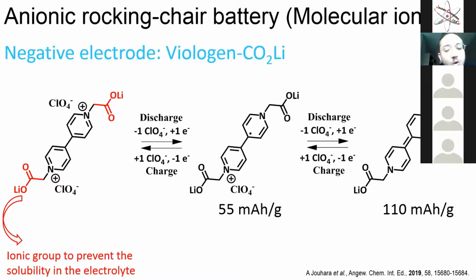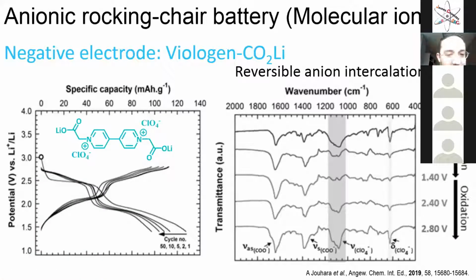This work has been published in Angewandte Chemie, and it is a nice work because it shows the real possibility of this viologen to be used as anode material for this molecular ion battery configuration. So here is the same redox reaction. In practice, as you can see on the left, you have the potential versus specific capacity curves. You start with a discharge at 2.5, you remove one perchlorate. Then you start a second discharge, you remove a second perchlorate. And you can do this reversibly. So take out, take in perchlorate.